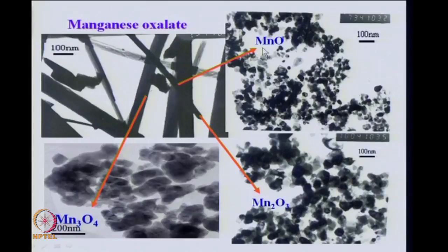So, you can get different oxide materials under different conditions of synthesis, like the decomposition temperature, and the environment in which you are decomposing is important. And if you have more oxygen in the environment, you will get more oxidized species of manganese. Manganese here is divalent, and here manganese has an average oxidation state of 8 by 3, right.